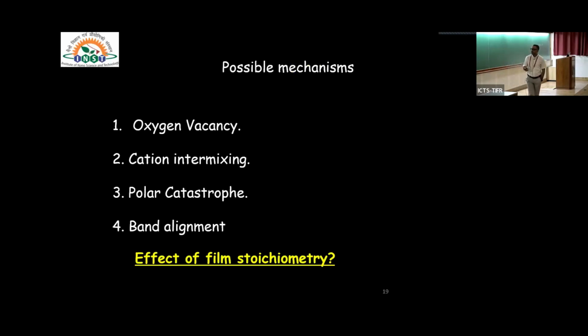One is oxygen vacancy, cation intermixing, polar catastrophe, and band alignment. We ask the question, what is the effect of film stoichiometry? So you have ABO3 deposited on A'B'O3. What happens if you change the ratio of AB stoichiometry?